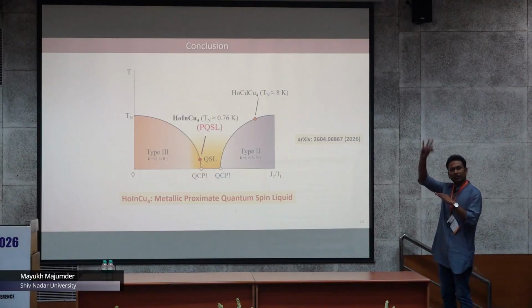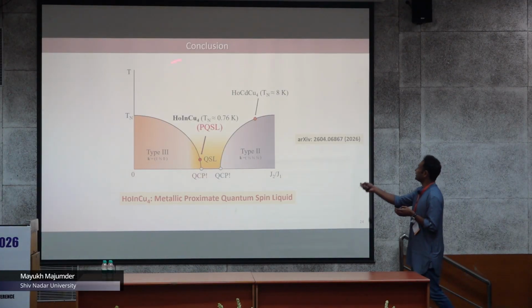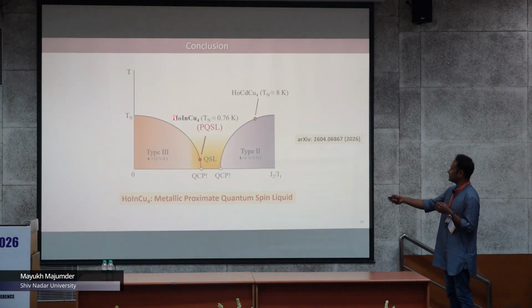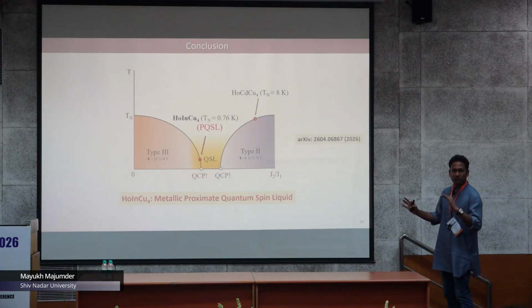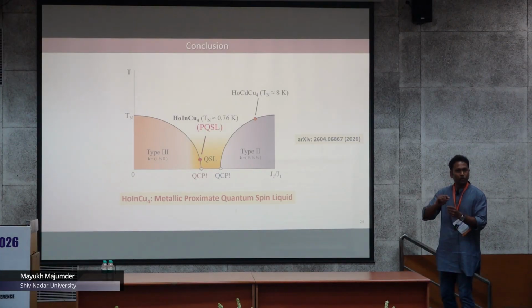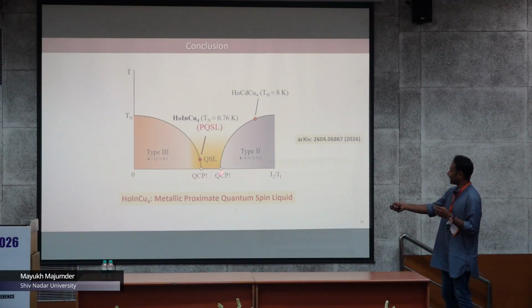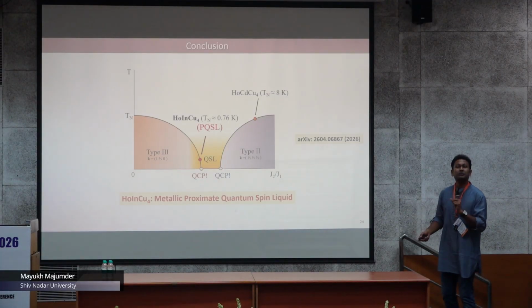So now, keeping all the points in mind, we constructed this kind of phase diagram. You can see that this is one of the compounds that I talked about, holmium indium copper 4. This is the proximate spin liquid state. We do not know whether there is a QCP or not, because we have not employed any other technique to really reduce the ordering down to T equal to 0, but we at least expect that there is a quantum spin liquid state proximate to this particular compound.